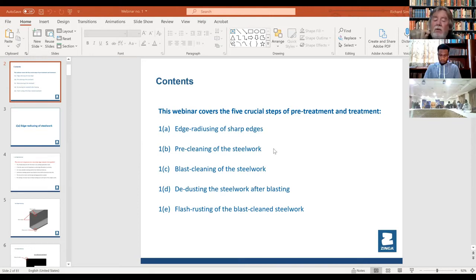If you go too shallow, you lose your pull-off values. Okay, with Zinga on a correct blast profile, when you do a pull-off test after 7 days, you're up to 6.5 megapascal, which is very, very high adhesion. And of course with high adhesion, you get better conductivity from the zinc, which gives you the voltage, which gives you your cathodic protection, and that protects the steelwork. So it all comes back to good blasting, good cleanliness, and the correct depth.